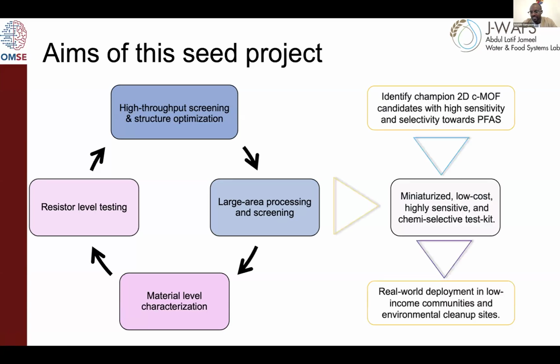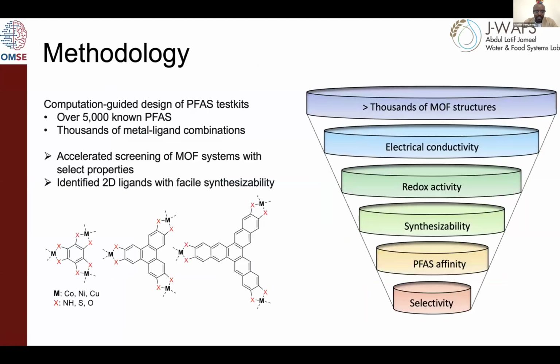And right now we're transitioning to this, to my right side here, where having identified a few materials that are promising, can we go into the low cost and scalable manufacturing of these materials into chemiresistive devices? And here, by chemiresistive, I mean materials that change their conductivity upon contact with PFAS. And of course, we're targeting real-world deployment, especially for environmental cleanup sites where these resistors can work. Our method, again, here we didn't want to take the approach that Tim is taking on conventional conjugated polymers. Here we're interested in conductive metal organic frameworks, or MOFs, where we have thousands of structures of MOFs that we can think about.